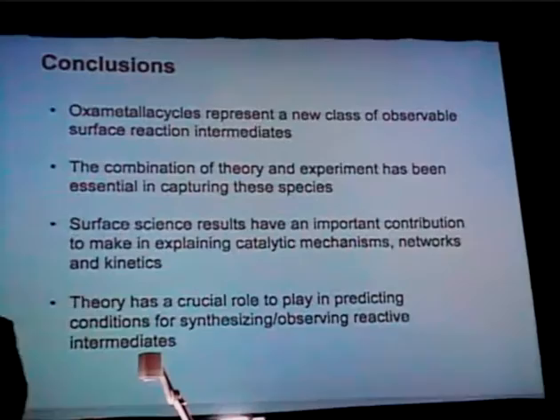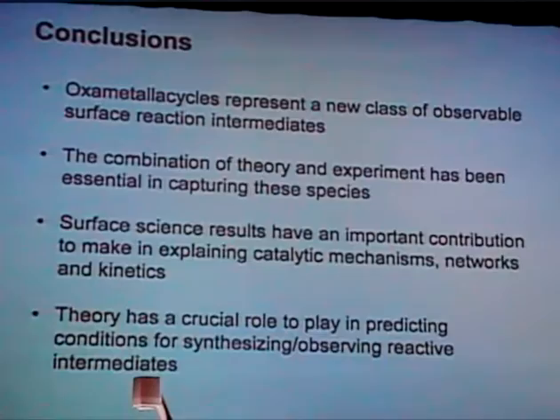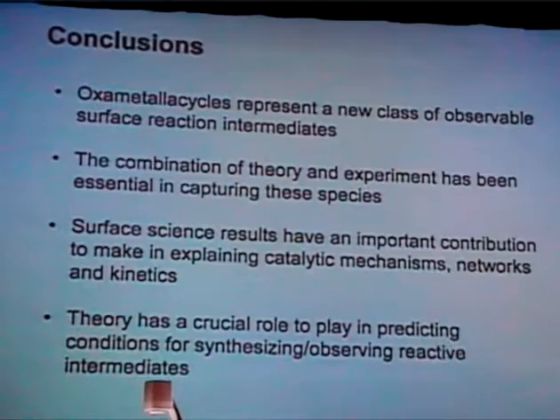So let me conclude. I think oxametallacycles represent a new class of observable surface intermediates. I hope I've shown you how the combination of theory and experiment has really been critical to understanding how to make these species and what they are when we made them. I hope I've shown you from the kinetic isotope effect experiments how we can make some pretty direct connections between these single crystal experiments and the things that we observe in steady state catalytic reactions. And in fact, that we now have evidence for some of those proposed stable intermediates in some of the complex reaction networks that have been proposed for this kind of catalysis in the past.